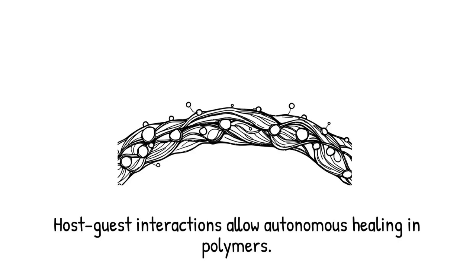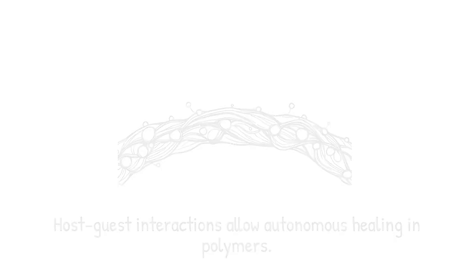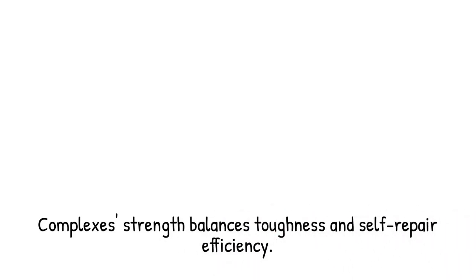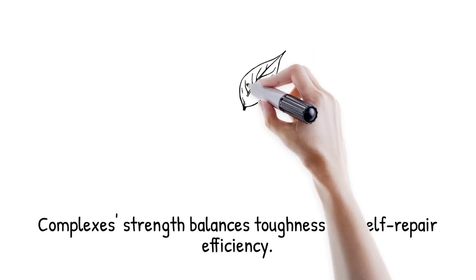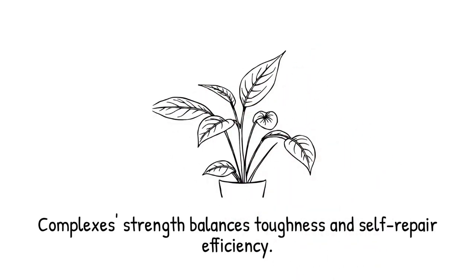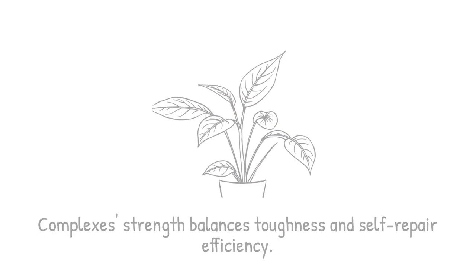These interactions are directional and selective, guiding polymer chains to reassemble at damaged sites. Upon network rupture, free hosts and guests diffuse and rebind, closing cracks without external input. The strength and lifetime of these complexes control the balance between material toughness and self-repair efficiency. Incorporating multiple orthogonal host-guest pairs yields hierarchical healing behaviors.